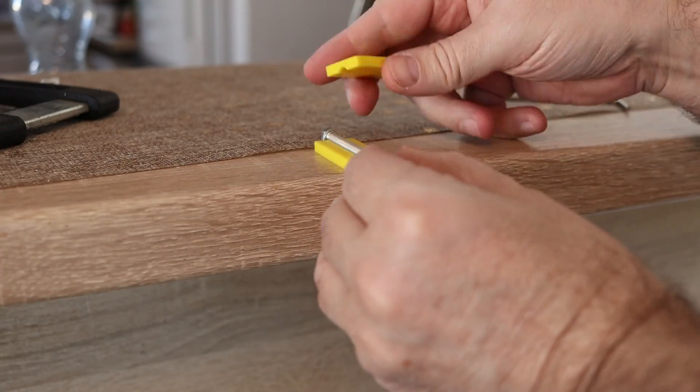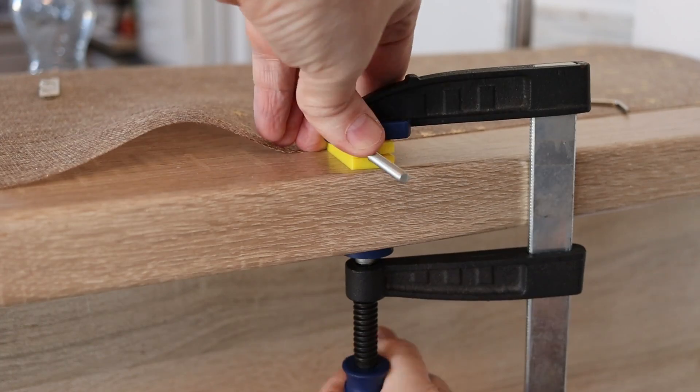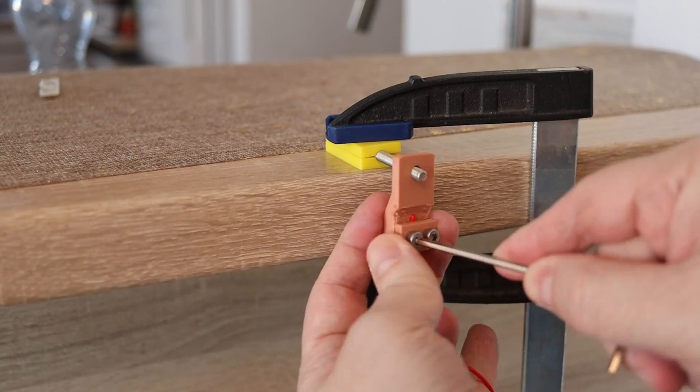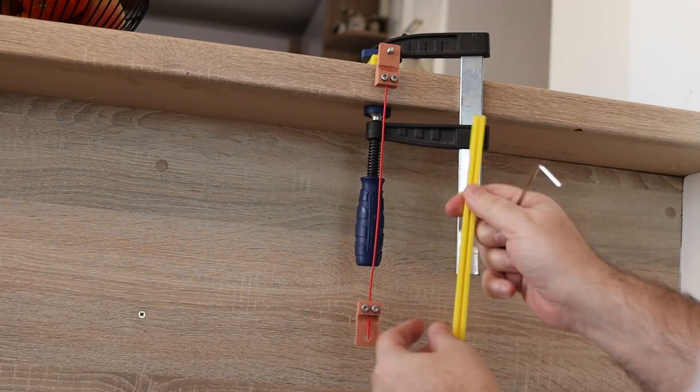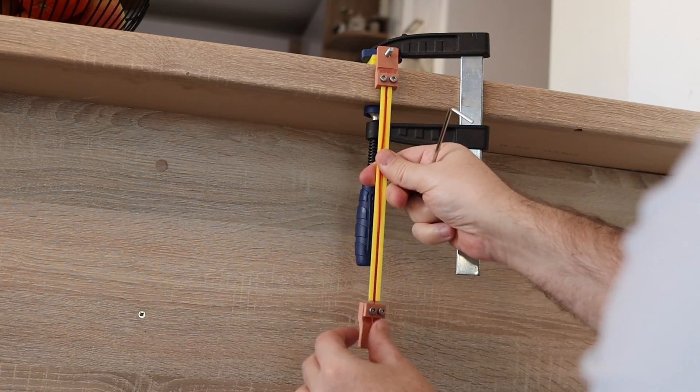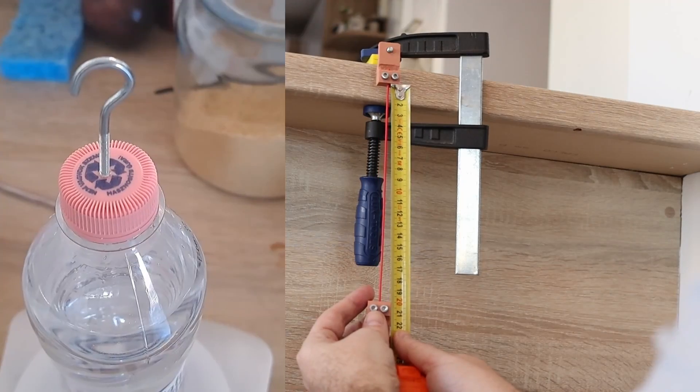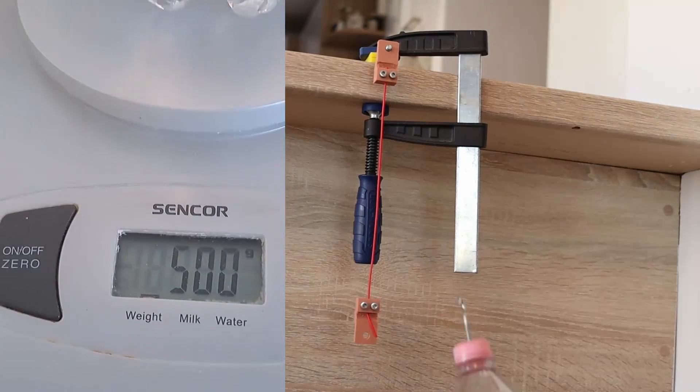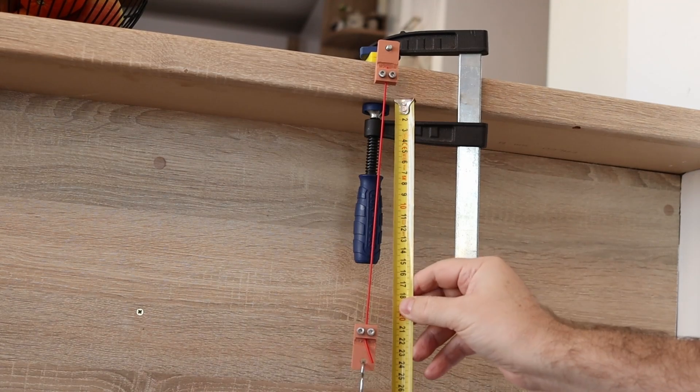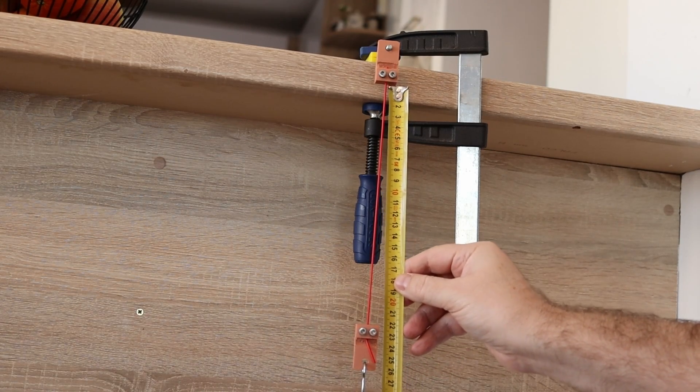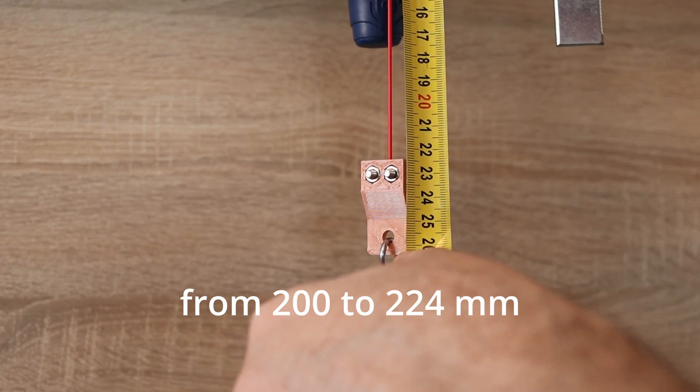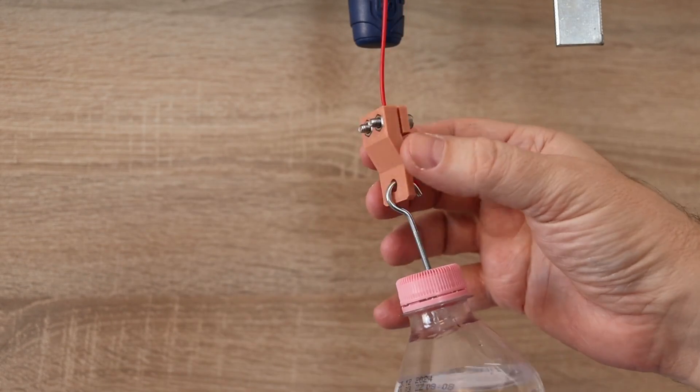Important filaments will be stored in some dry place. This is that new testing method and I will repeat it with all TPU filaments I tested so far and add it to that Patreon summary table. This is the holder for the filament, and this is the tape measure, exactly 200mm long. As you can see, 200mm by default and I am placing exactly 0.5kg load on it. After exactly 0.5 minutes I am measuring the new length which is 224mm in this case. And here I am removing the load.